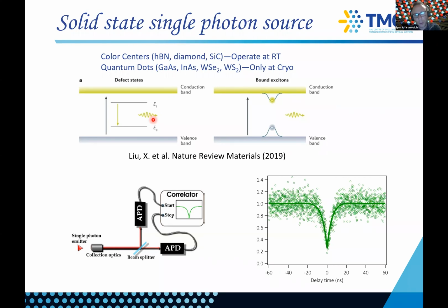And so the first measurement that you would probably do in the lab if you're studying these systems is an autocorrelation function, which means that you would split your signal into two detectors and measure correlation. And a dip here at zero delay time means that you have no correlation at a specific time, which indicates that you have only one single photon source in your system. So you will see quite a few of those g2 functions throughout my talk. And these are just evidence that they are single emitters.